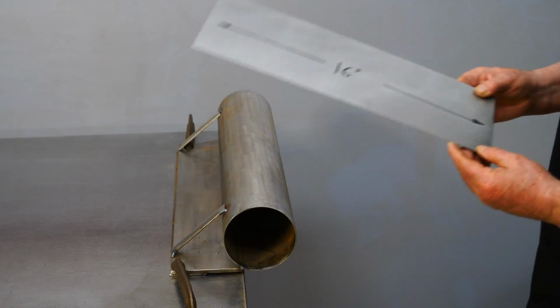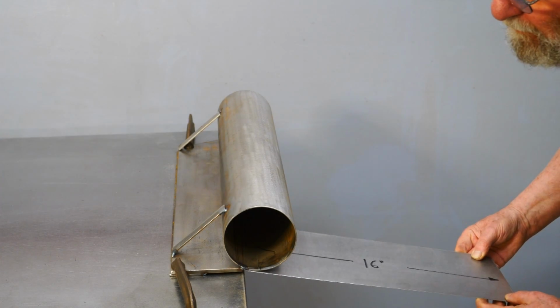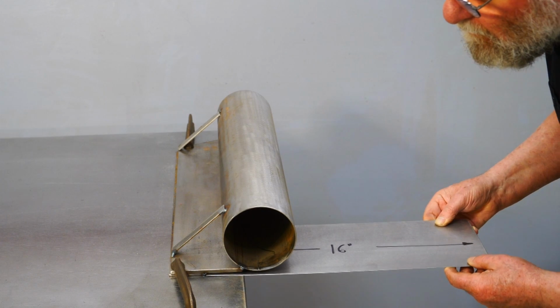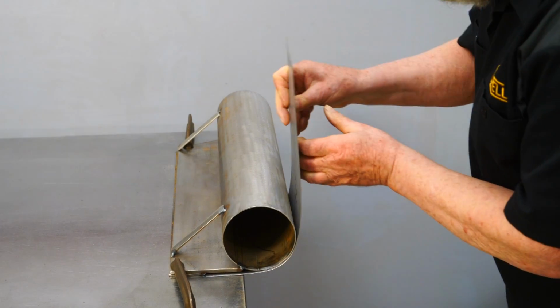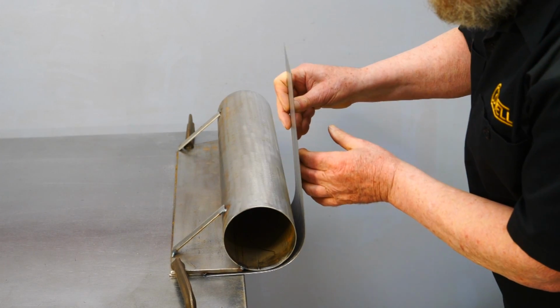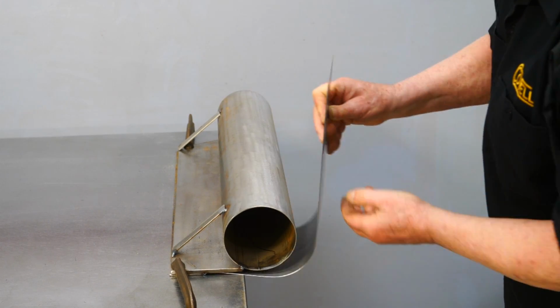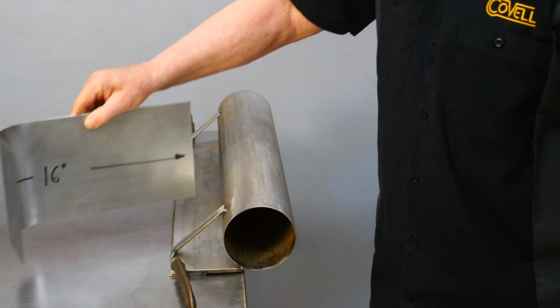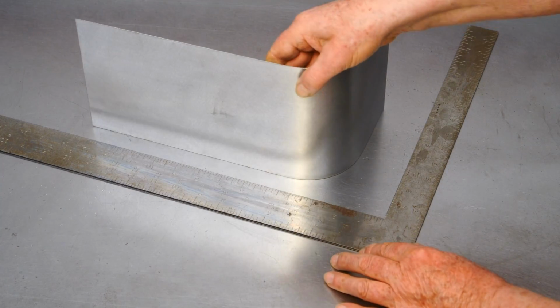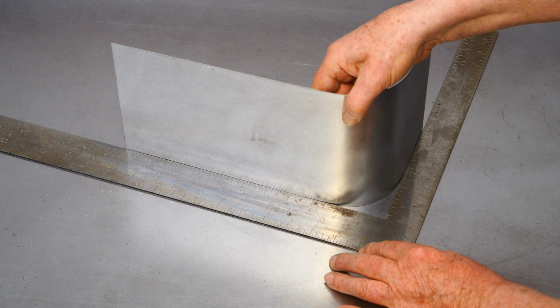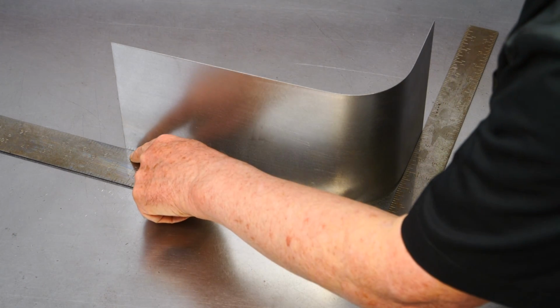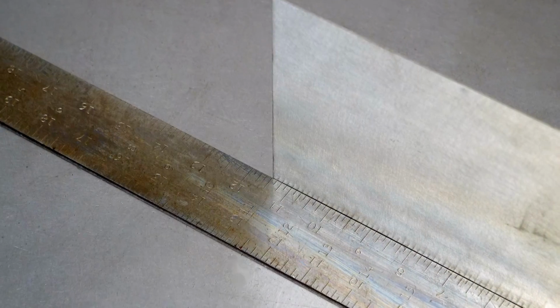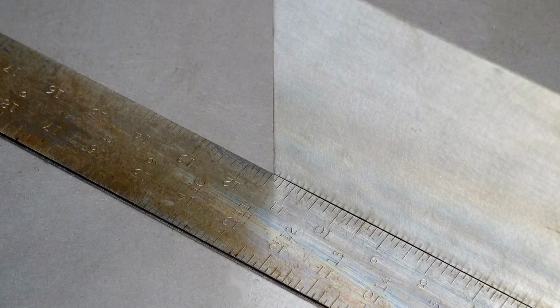I always do a test piece, since different material types and gauges will spring back differently. As long as you push the metal in until it touches the stop, each bend will be repeated exactly. There's no need for measuring. I start with a piece of known length, 16 inches in this case, and then I measure how much the part has shrunk. In this case, the width shrank 4.5 inches. The principle is the same for metric dimensions, of course.